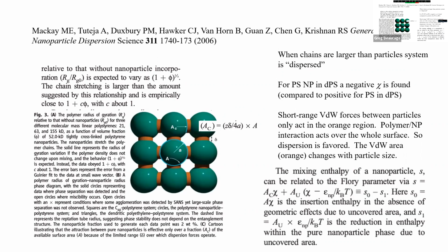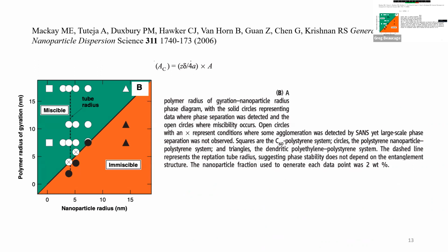So he comes up with this scheme to explain why these beads are separating out. Let's see. This is his phase diagram. So this is the first kind of real phase diagram for polymer nanoparticles. This is the size of the polymer that's going in. This is the size of the particles that are going in. And he finds out that if those two match, that's his critical point. That's where he gets phase separation. So if you have big particles, they're immiscible. And if you have large polymers, they become miscible.